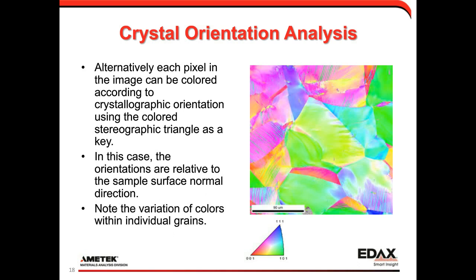Alternatively, we can go a little bit further and color each pixel according to the crystallographic orientation. In this case, you can see there's a little stereographic triangle that's colored. Red points would be a 001 orientation, blue would be a 111, and green would be a 101 orientation. The steel alloy is a cubic alloy, and that's why this stereographic triangle is used. In this case, we're shading the colors relative to the surface normal direction of the sample.